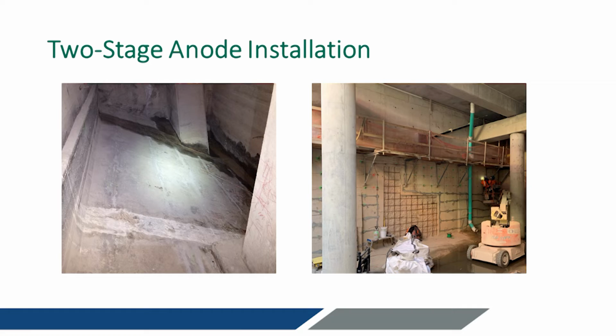And then here again, you see this is the abutment wall, so they have a concrete repair, so that's all physically damaged now, but the rest of the crosswall has a high risk for corrosion, so they're going to do the anodes in those other areas. So really targeting where they need to prevent corrosion.